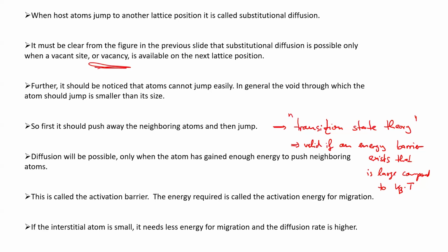If the energy barrier is sufficiently high, then the normal motion will not be sufficient to overcome it, because kBT is not enough on average to go above the barrier. That means you have to have a rare excursion, a rare event. And in statistics, rare event statistics are used to describe these processes. For example, Poisson statistics is typical for these types of processes.